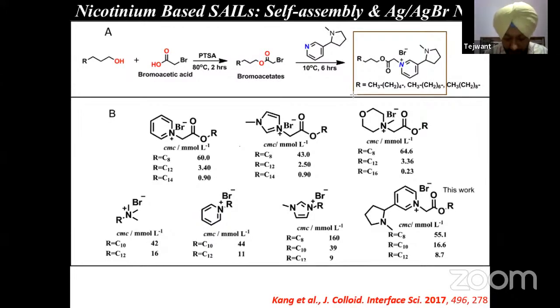So when we transform the nicotine to nicotinium cation and append it with the alkyl chain having the ester functionalization, then with the presence of this ester functional group, the ionic liquid behaves much superior to the conventional reported surfactants in terms of its critical micelle concentration. Critical micelle concentration is one of the important characteristic parameters of any surfactant, which should be as low as possible. So we have compared the critical micelle concentration of the prepared surfactant to that of many of the reported ionic liquids and surfactants, and it was found that the prepared nicotinium based surface active ionic liquid exhibits much lower CMC as compared to the reported ionic liquid surfactants.